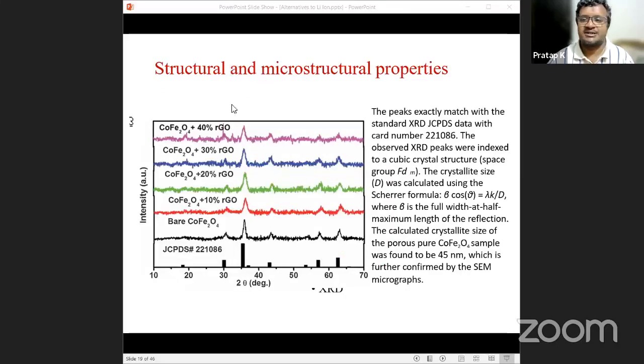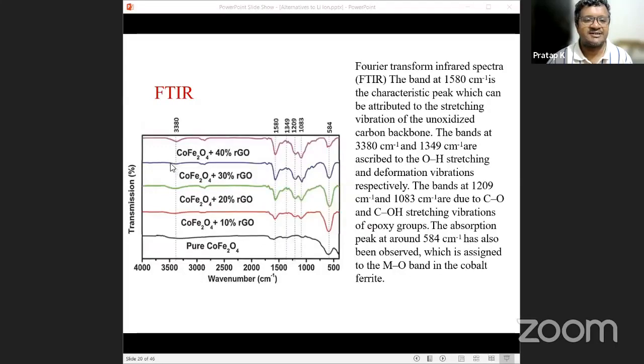So these are the structural and morphological studies. So bare cobalt ferrite, 10% RGO cobalt ferrite, 20% RGO cobalt ferrite, 30% RGO cobalt ferrite, and 40% RGO cobalt ferrite. So everything showed really pure peaks of cobalt ferrite formation. And this is the FTIR. So again, the same thing. Black one is the pure cobalt ferrite, red one is 10% RGO plus cobalt ferrite, green one is 20% RGO plus cobalt ferrite. The dark blue one is 30% RGO plus cobalt ferrite, and 40% RGO plus cobalt ferrite is somewhere here in maroon color.